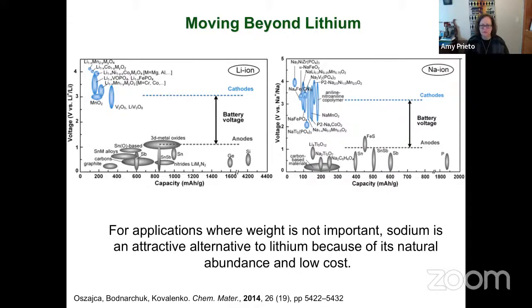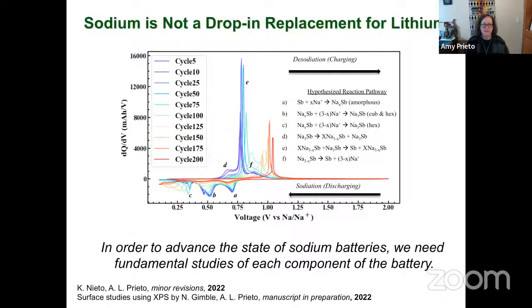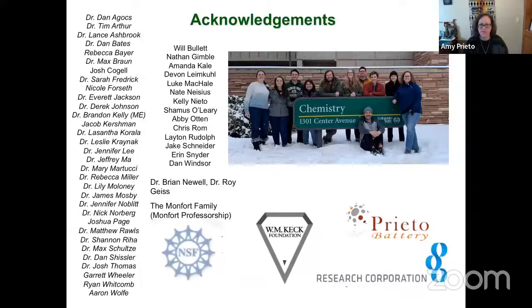The very last slide, we can use differential capacity plots to study, in this case, antimony sodiating and desodiating. We see a lot of change over cycle number. We can assign each of these peaks to a distinct reaction, and we're seeing some pretty interesting chemistry that's happening from pressure in the films and the ability to access kinetically stable phases that can help us store a lot of sodium. So with that, I just want to thank my group and the funding agencies.